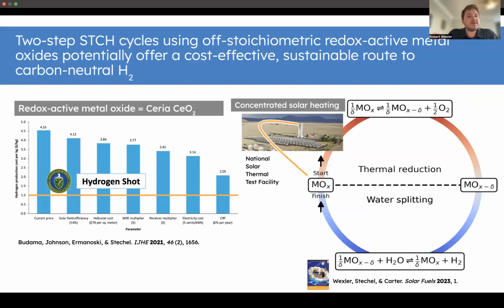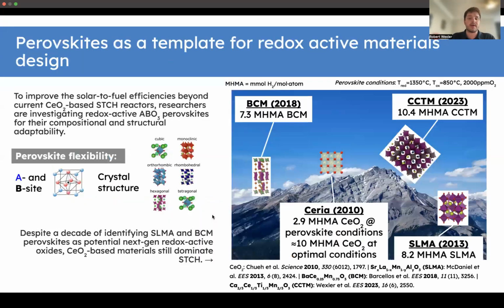Okay, so two-step solar thermochemical hydrogen production cycles using off-stoichiometric redox-active metal oxides like CeO2 potentially offer a cost-effective, sustainable route to carbon-neutral hydrogen. Here on the left, I'm showing a recent techno-economic analysis by Budama, Johnson, Ermanowski, and Stechel, which shows on the y-axis hydrogen production cost in US dollars per kilogram, and on the x-axis a series of different considerations that could lead to a reduction of the current price, which is $4.5 per kilogram hydrogen, to somewhere around $2 per kilogram hydrogen.